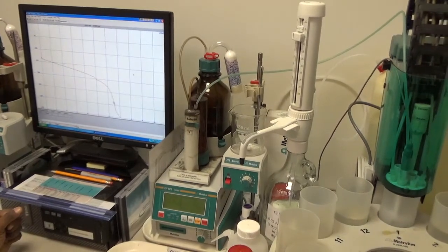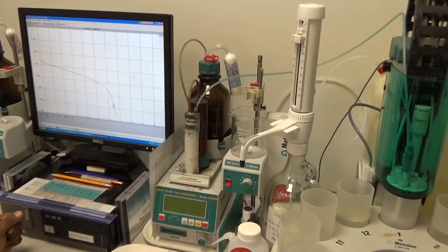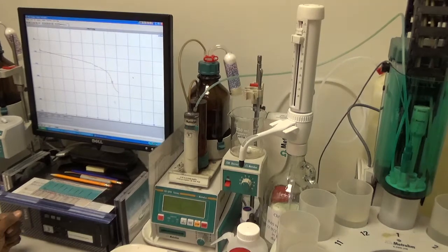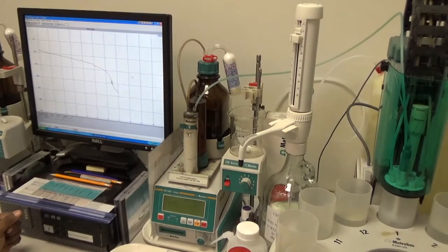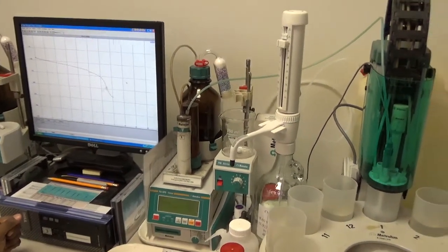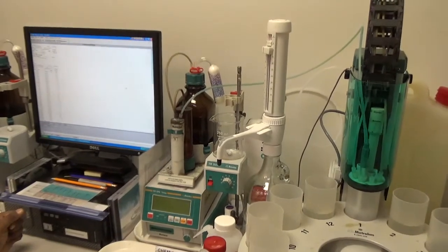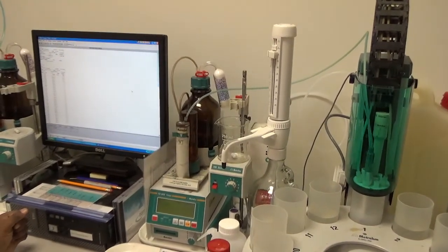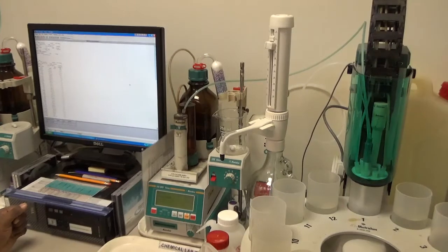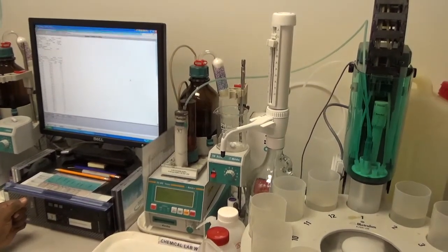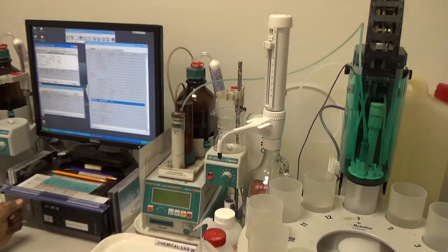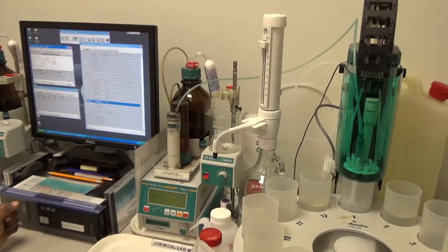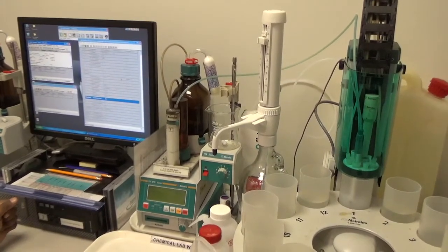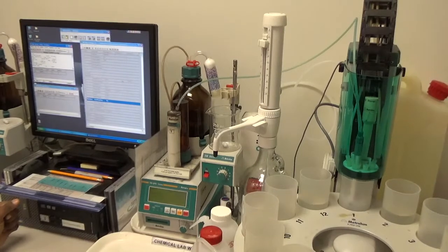And then here it is. It found the equivalence point with the green circle. So once it finds the equivalence point, it came around 6.5. It gives the result and it shows the chloride content 0.23% on that solution. It shows where the EP was found, where the equivalence point was found, and then it calculates the chloride content.